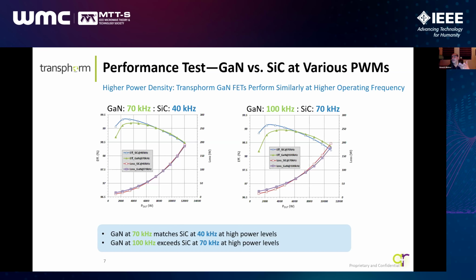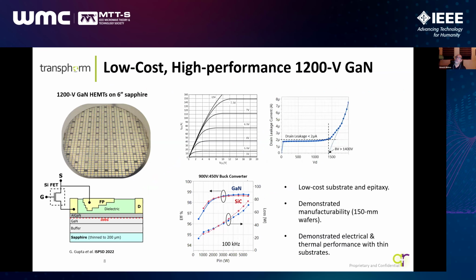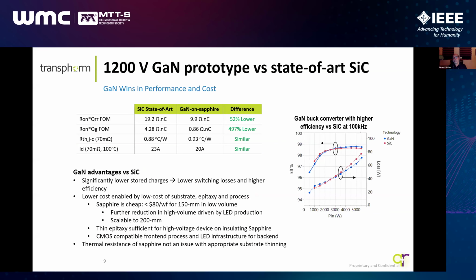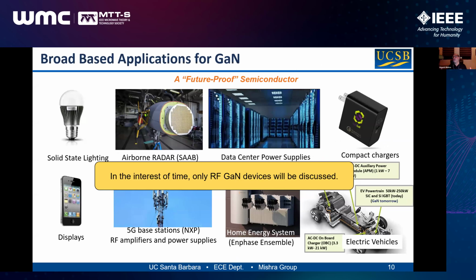But my mantra is that it's going to be a flip in about a decade. And the reason is that gallium nitride can also do things that were typically not thought possible with gallium nitride. Here's a gallium nitride transistor with a breakdown voltage of 1200 volts, which can now deliver performance very similar to silicon carbide. The message from this part of the talk is very simple. If you have a future-proof semiconductor where the semiconductor not only serves the microwave market, say 5G as an example, but it serves huge markets associated around, which means that the microwave performance to cost ratio will be good.